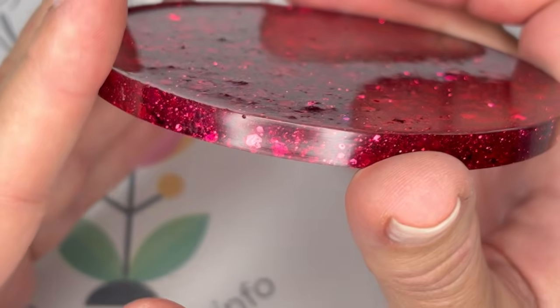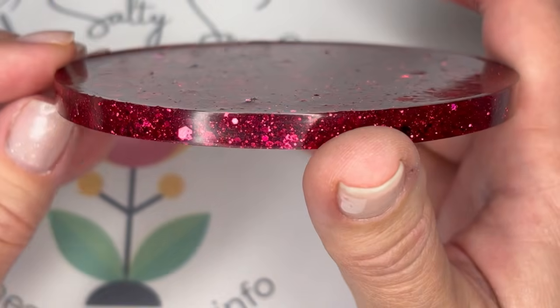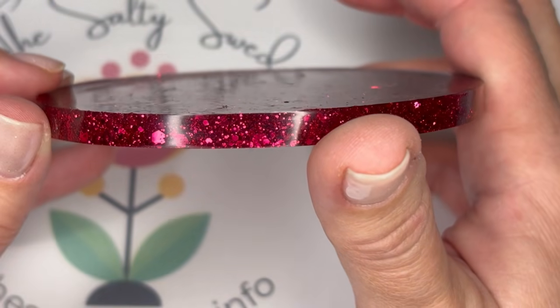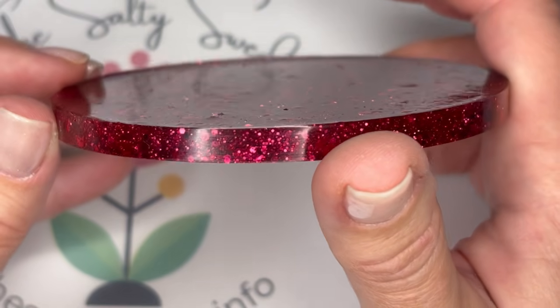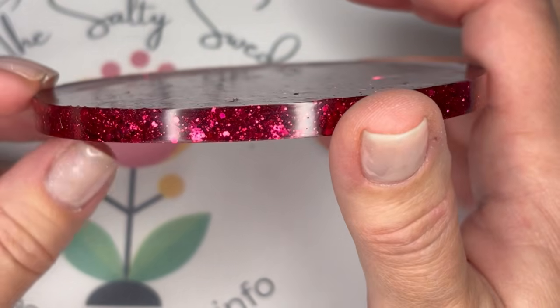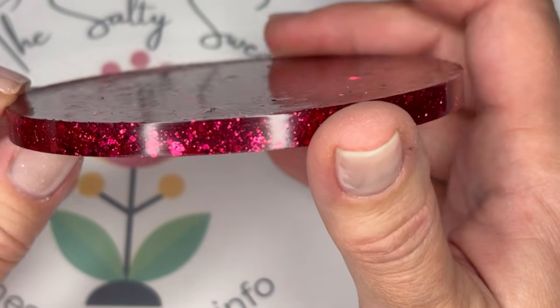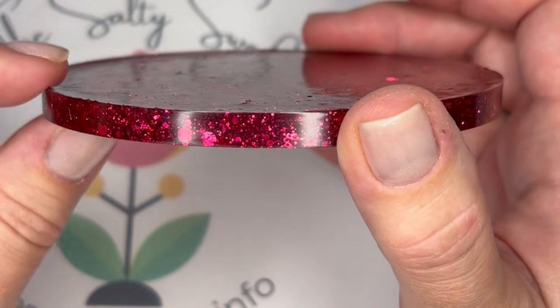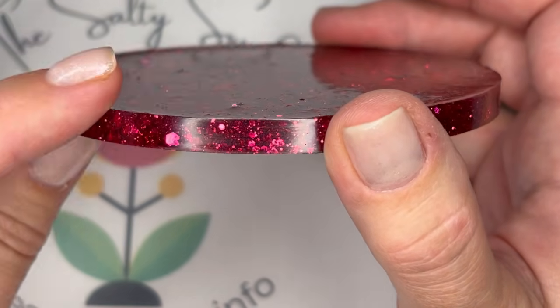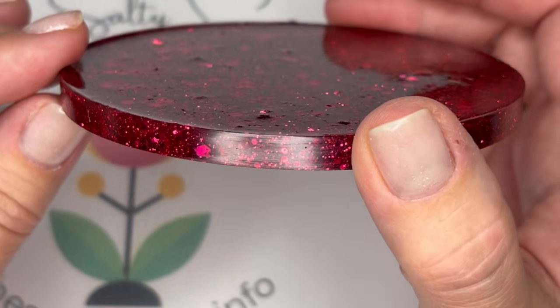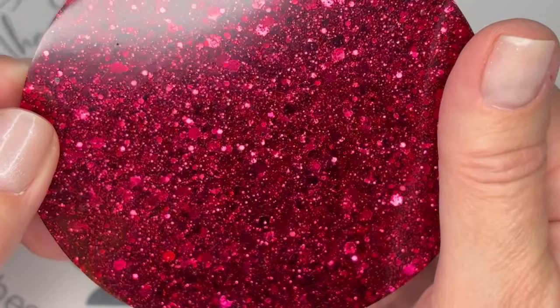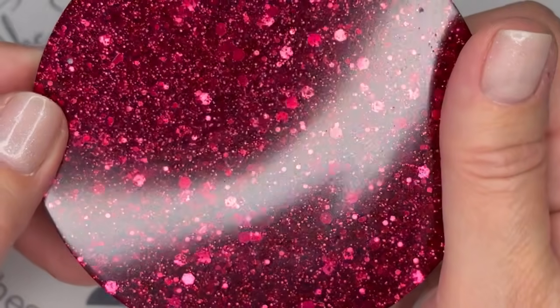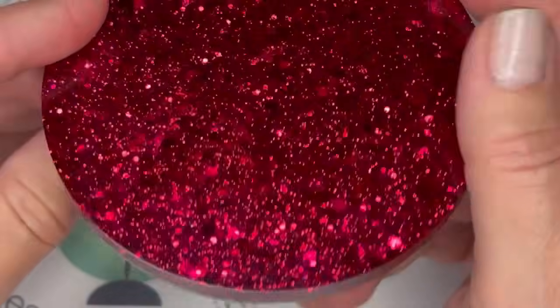But now that it's out of the mold, I can see that there's a lip around the top edge. This happens because resin shrinks as it cures. It's totally normal, and you can sometimes avoid it, but that takes some practice. For now, we'll deal with the lip in another way. In fact, I'm going to use it to my advantage when I pour a top coat on this thing later. This edge is kind of sharp, and it'll take a bit of extra resin to fill that up to the brim, so I'll show you how you can fix that.